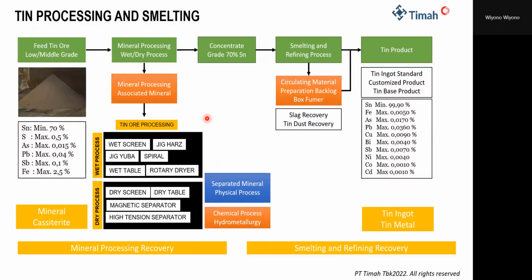Physical properties that we use, at least three. The first is difference in specific gravity, the second is conductivity or electrical properties, and the third is magnetic properties. We use the differences in these three properties to separate the tin mineral, in this case cassiterite, from the associate minerals. From the mineral processing, we will get cassiterite with a minimum grade of 70% Sn.